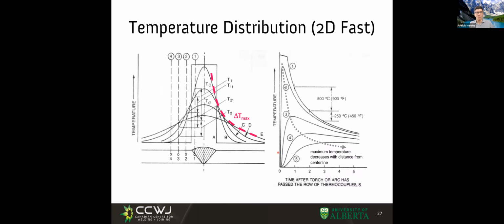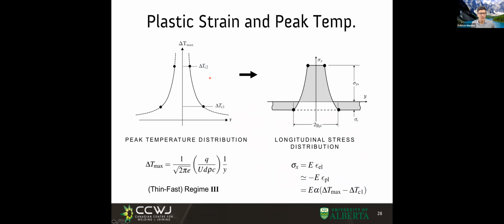So what do we see? We have seen when we started to discuss our module on temperatures that the farther away we were from the weld, the lower the maximum temperature was. And this is a schematic of each point, what is the maximum temperature it would see. Now, this maximum temperature multiplied by the thermal expansion coefficient gives us the total strain. And we said that any temperature above the yield temperature would result in plasticity.